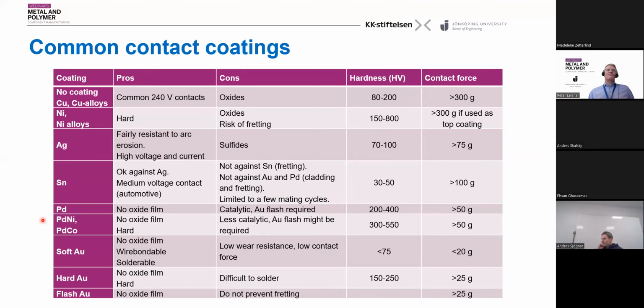Then we have palladium or palladium alloys as an alternative to gold as a precious coating. It forms no oxide film, is quite hard, and needs a quite low contact force. Pure palladium is a catalytic material, so therefore you might have the risk that pollutants from the air can react on the surface and create contamination. In that case, it could be wise to have a thin gold top layer. If you have the palladium alloys, this risk is less.